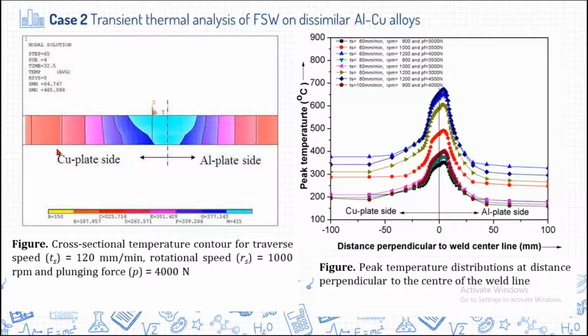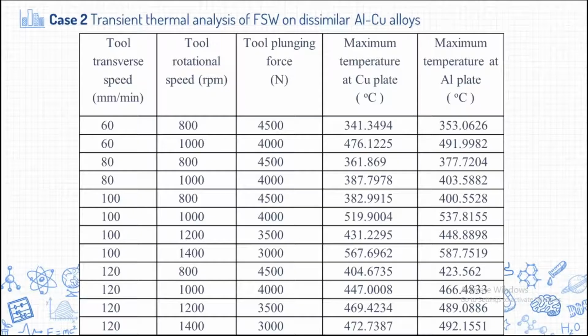So these temperature values from the center of the welding, going away from the center, we plotted on a graph for all the various process parameters, like 60 mm per minute, 800 rpm, 3000 Newton. We varied all these process parameters and plotted them on a graph. And these are the various values for maximum temperature near the copper plate and maximum temperature at the aluminum side, and these are the various process parameters. Around these parameters are giving a good temperature to get a good quality of weld.